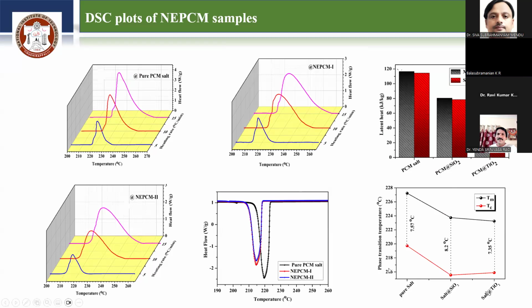In this phase transition temperature, we can see the melting point for pure salt is at 228, whereas for SiO2 it is 224, and it is further reduced for TiO2. So this clearly shows that these materials can be used effectively for thermal energy storage.